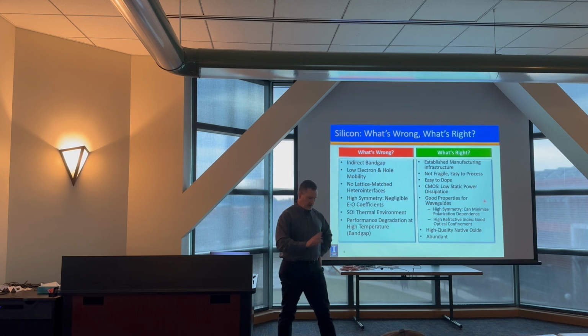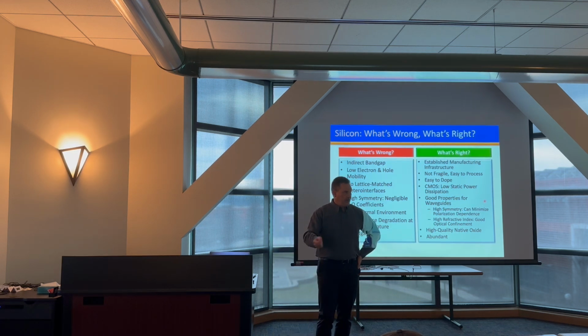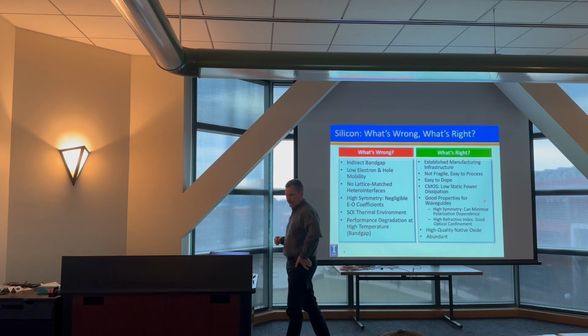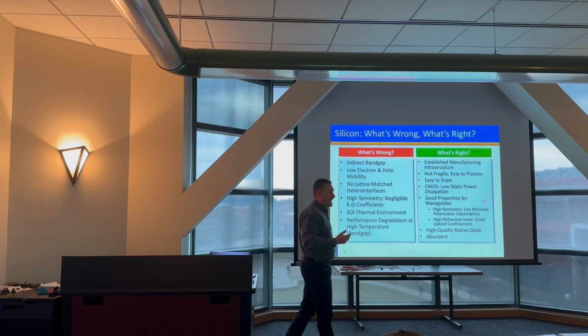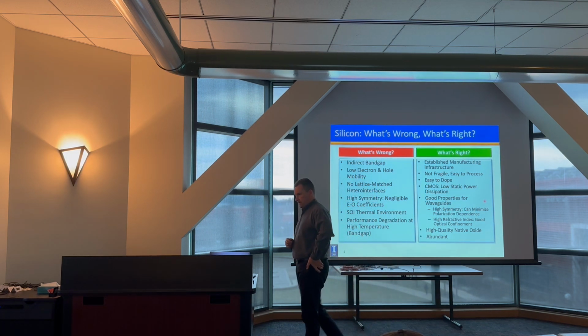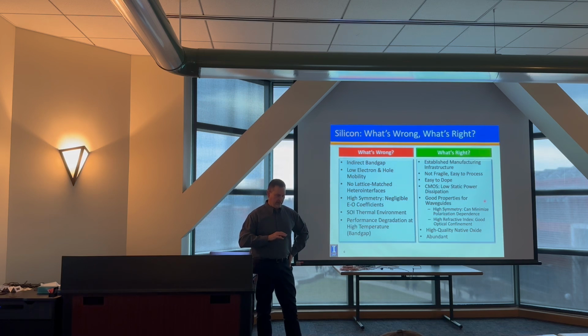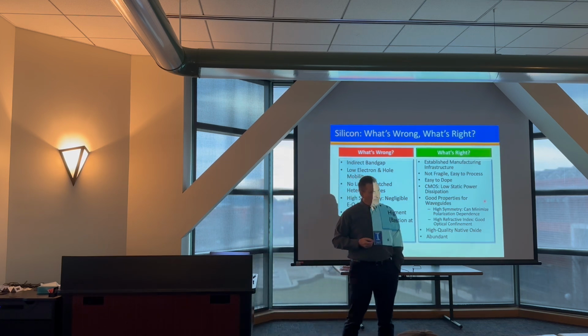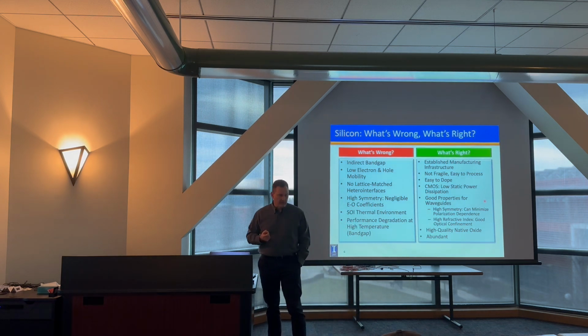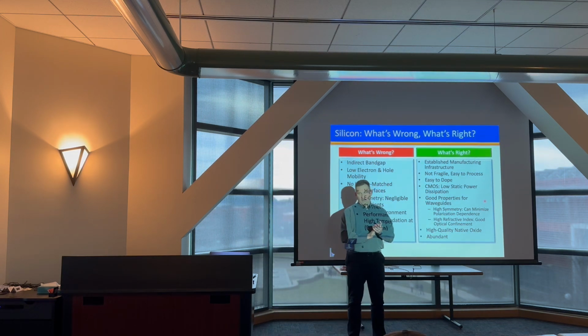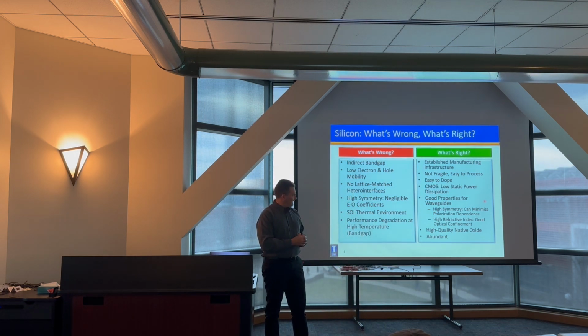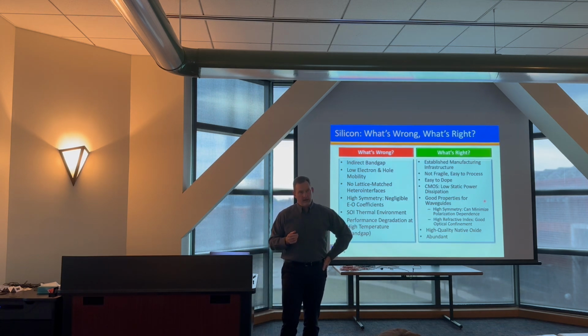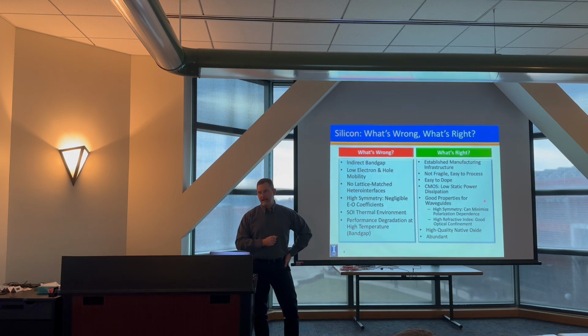And it's abundant. Literally, I can almost go to the beach, fill my pail up with sand, and then go through a lot of refining processes, including fractional distillation. I convert my silicon oxide into silicon, I convert that into a liquid, I do fractional distillation, and then I turn it back into silicon. But I can make very high purity material from a very abundant supply. Now, that's qualified a little bit. As it ends up, there are better places than others to get your SiO2, but it's abundant. It's not like other materials, the 3-5s for example, where there's a more limited amount. There's a finite amount of gallium.